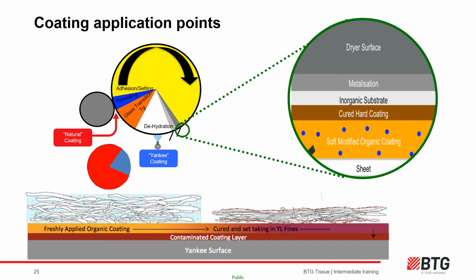The hard cured coating is residual coating chemistry and paper making contamination, as we've discussed, and the orange layer is a more flexible, hydrated and robust organic coating, which has gone through the glass transition and stuck the sheet to the cylinder. The blade sits in this layer, having cut through the sheet when initially applied, and crepes the sheet and removes it, or refreshes some coating rather, from the cylinder. The blade is the black object to the bottom left.